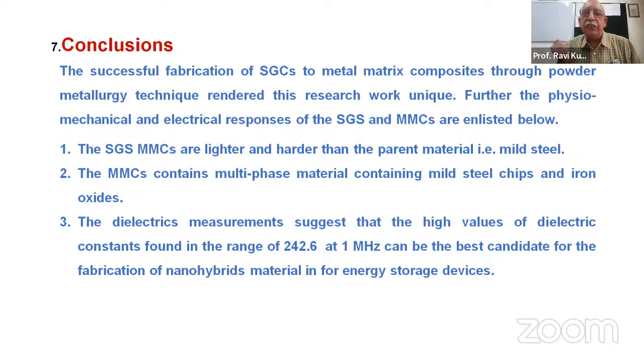The dielectric measurement suggests a high value of dielectric constant, in the range of 242 at 1 megahertz, 242.6 dielectric constant at a very high frequency. So these materials can be used for high frequency devices, whereas other kinds of ferroelectric materials we are using have very strong dispersion, and their losses are also high. So it can be the best candidate for the fabrication of nano hybrid material in energy storage devices.